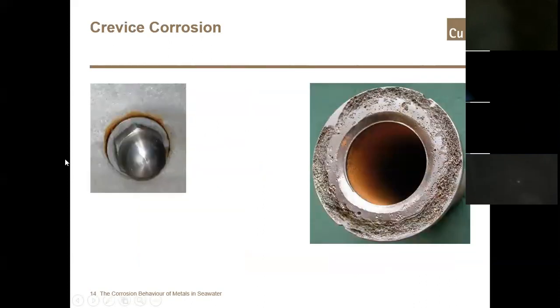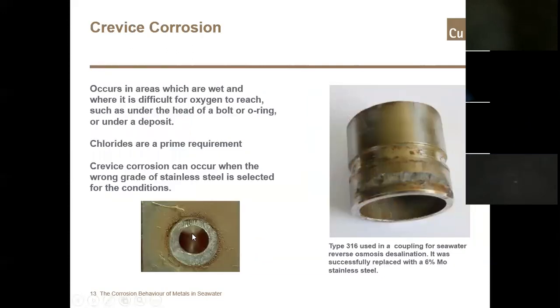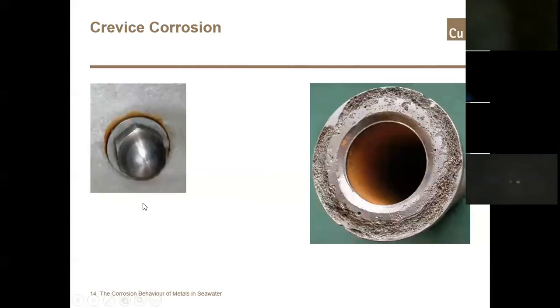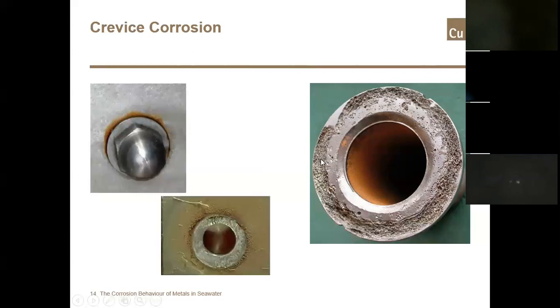Again, if we go back to the previous image, this is where the nut sat in the component, and you can see around the nut before it was removed that there is some rust, and then from that rust, when the nut is removed, you can see the crevice corrosion underneath, on the surface and also on the parent material itself.